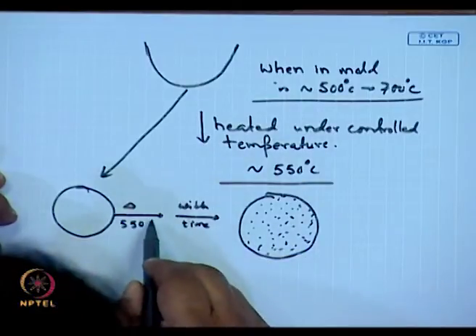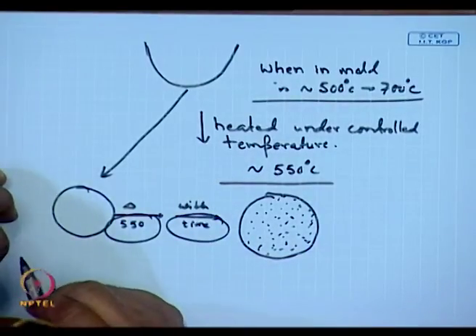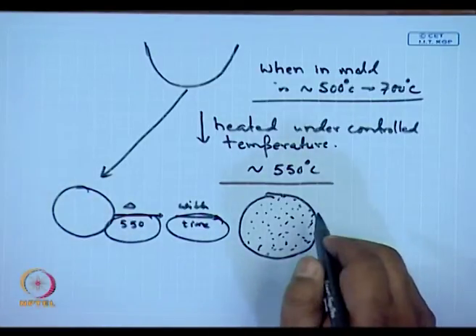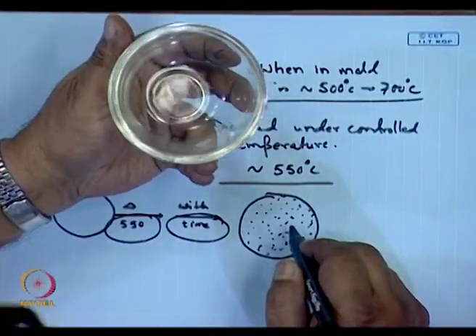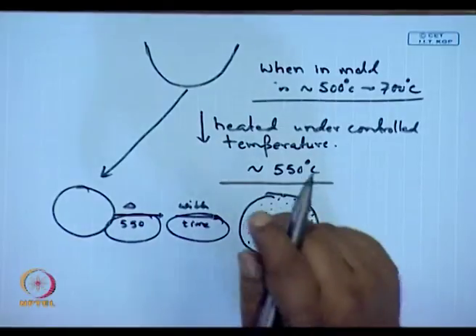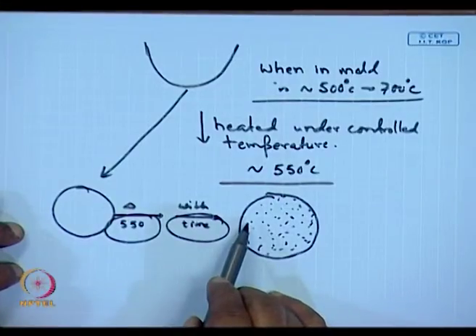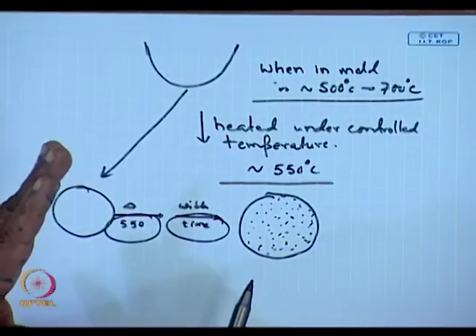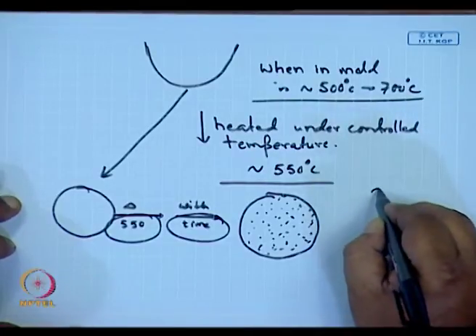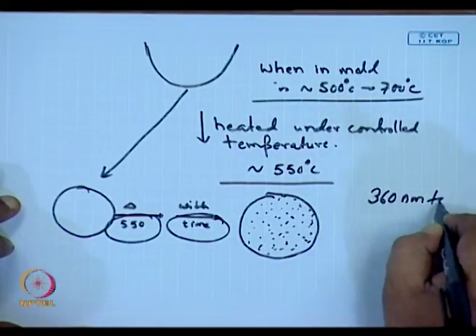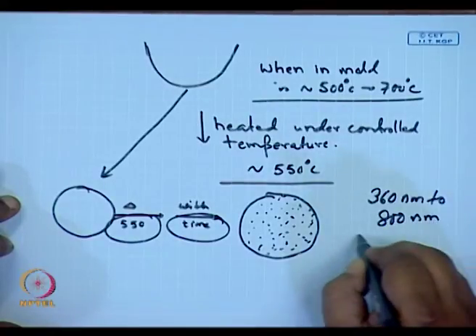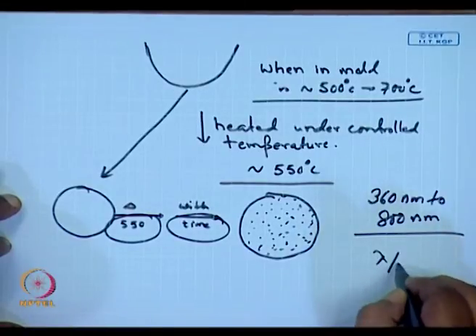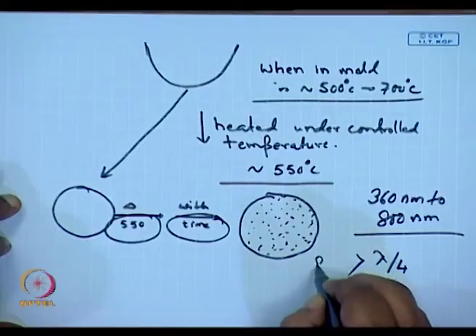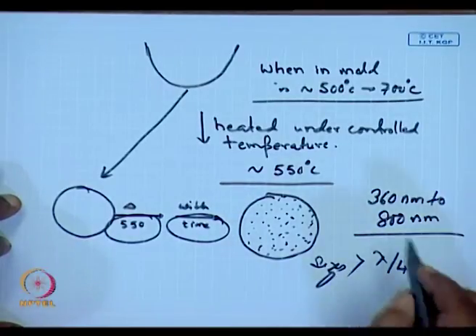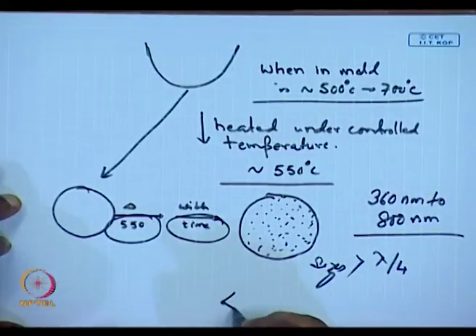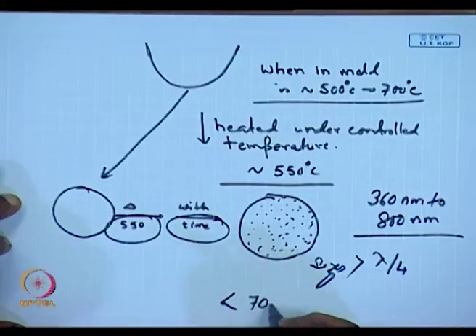This temperature and this time have to be calibrated, because if these particles become too thick, this glass will not be transparent anymore. So we have to ensure that these particles are finer than the scattering diameter. The wavelength of light is anywhere from 360 nanometers to 800 nanometers, and hence scattering will occur at sizes greater than lambda by 4. So here we need to maintain particle sizes below, let's say, 70 nanometers.